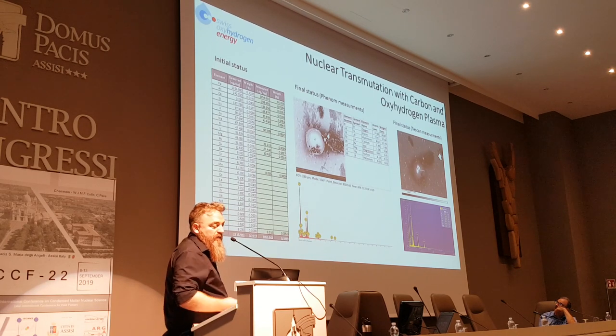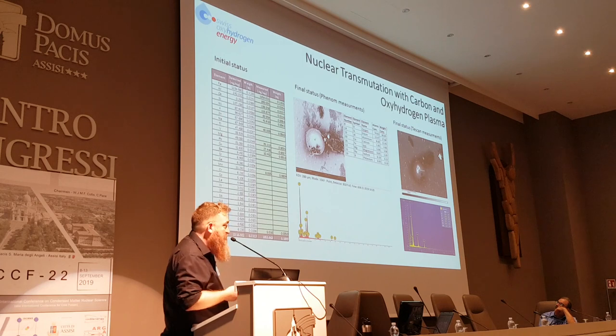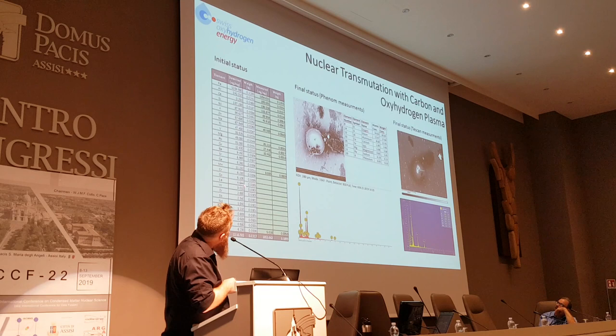The graphite was analyzed before treatment. You can see here the result of the screening first, and then the precise measurement of different elements that I found in these spheres. I didn't ask to make all the precision measurements of all these elements. For the graphite rod, you can see that about 99.8% is carbon, and only 0.2% is all this. The component that is mostly in the graphite was iron, 0.12%.